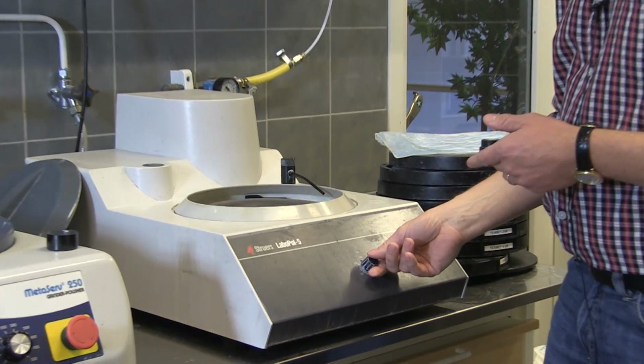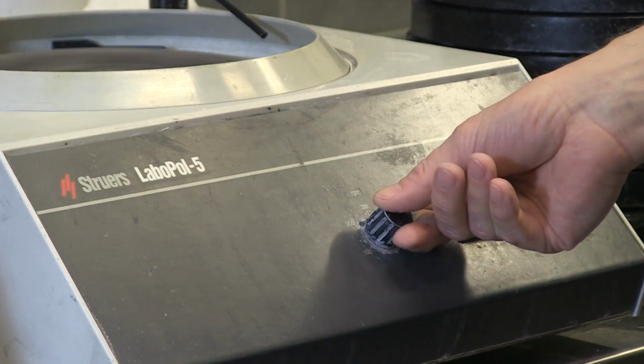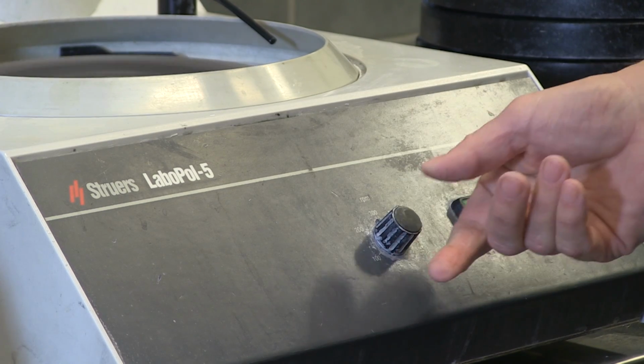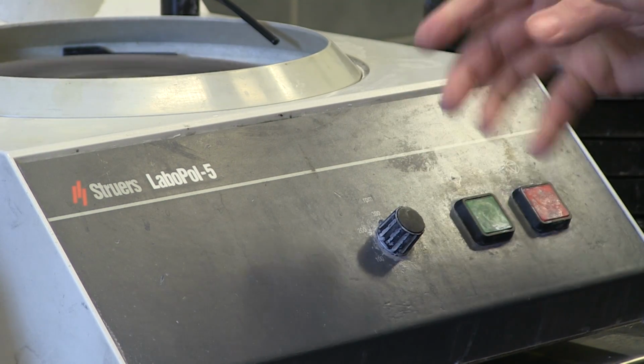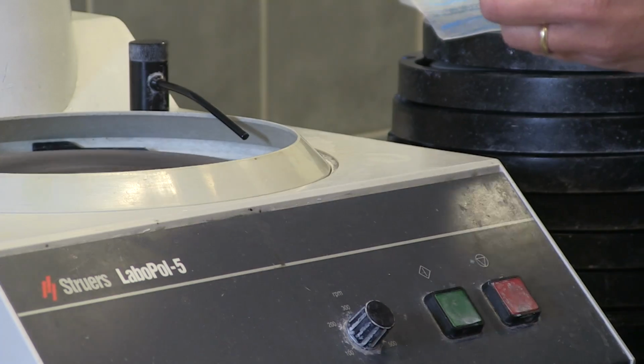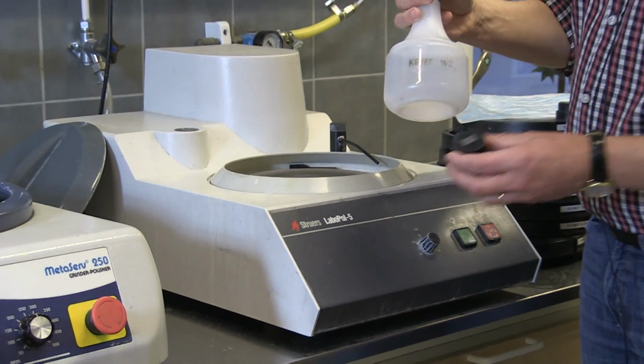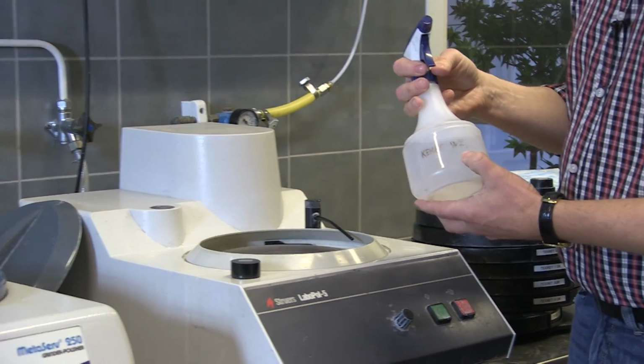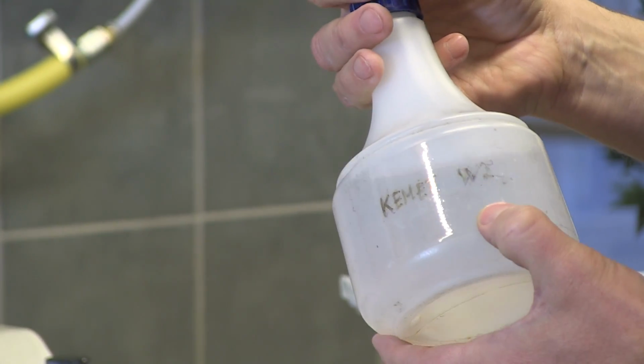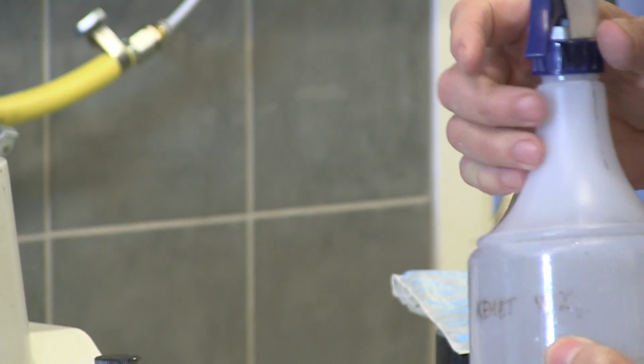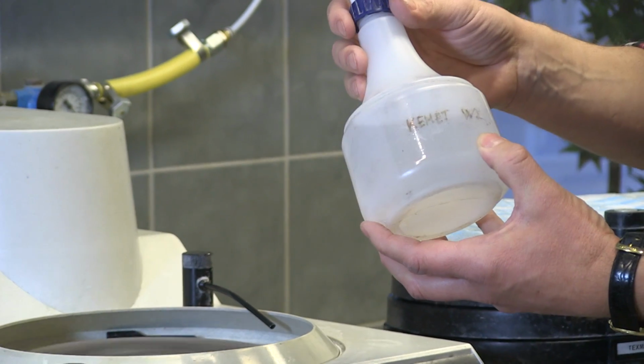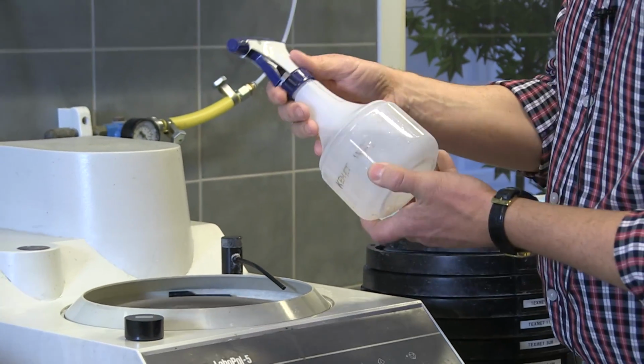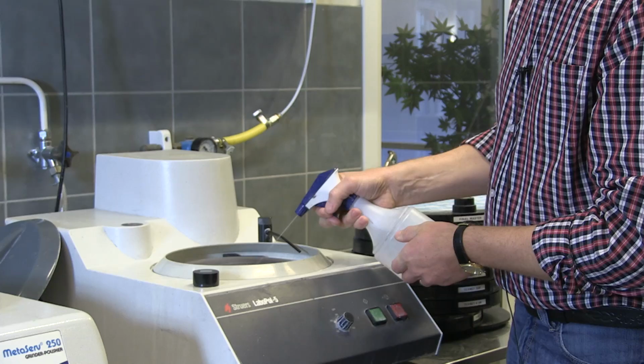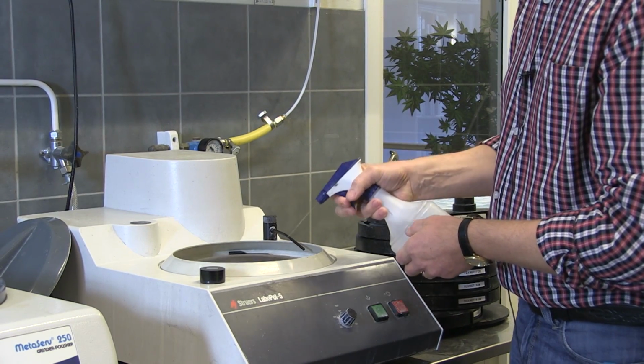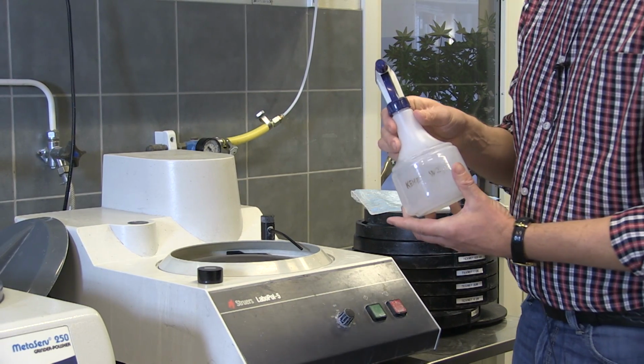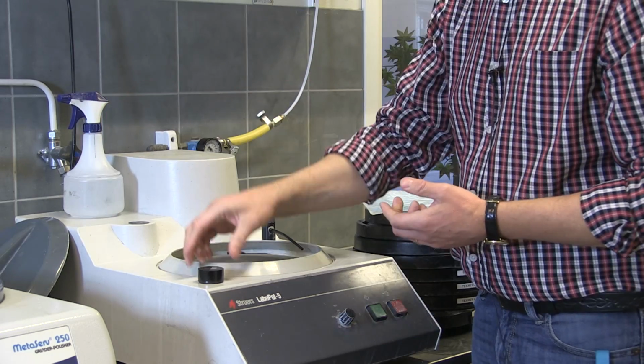Same here, you can adjust the speed. Adjust it to something where you think you're comfortable with holding the sample, around 300 for me. Also, you will need an extender. It's called Kemet W2. It's very difficult to read here, but it is water-based. It's mostly water with some additive. And this is added because we don't want the surface to be dry. It must not be wet, but it should be moist.